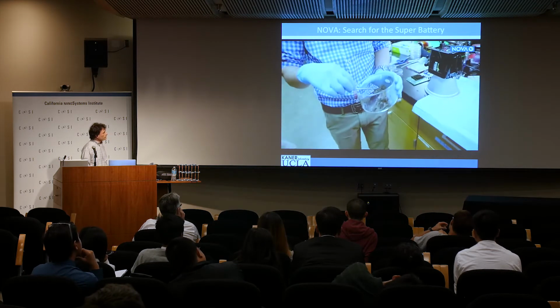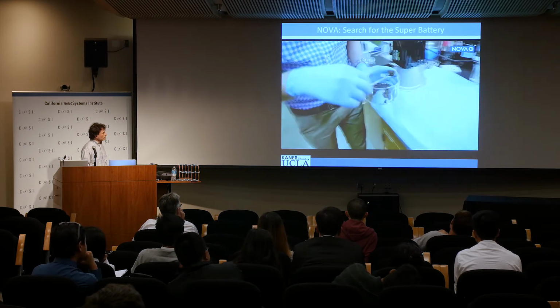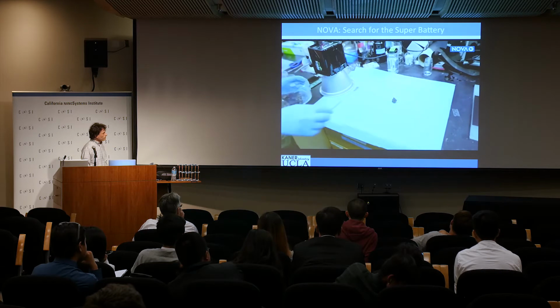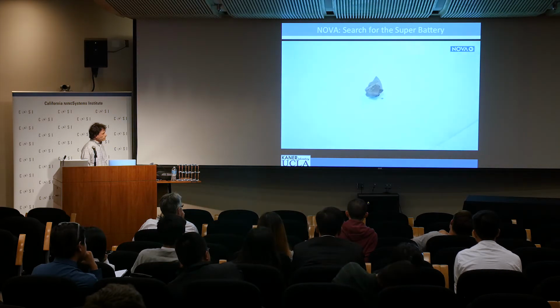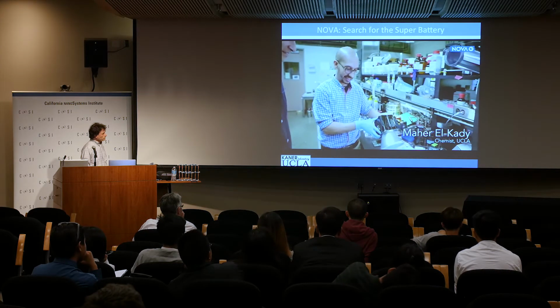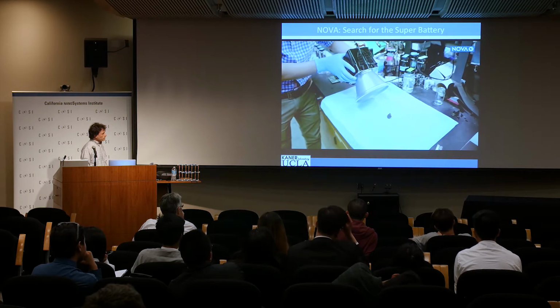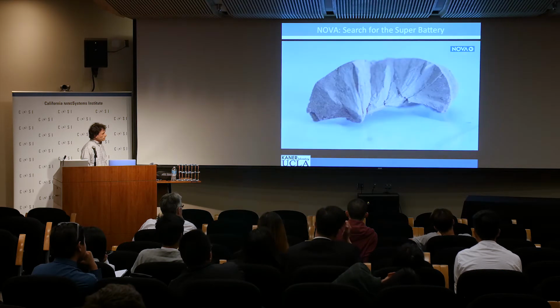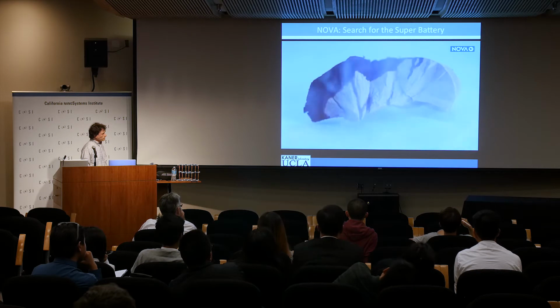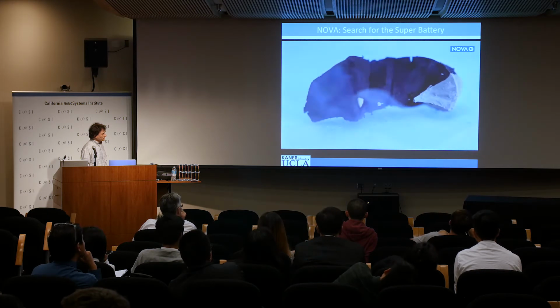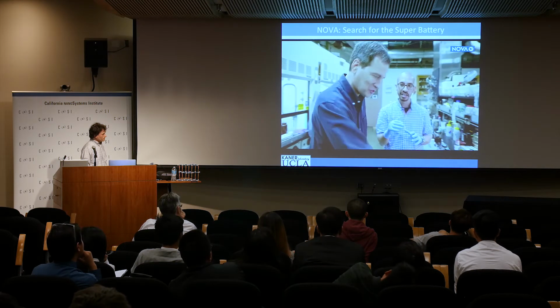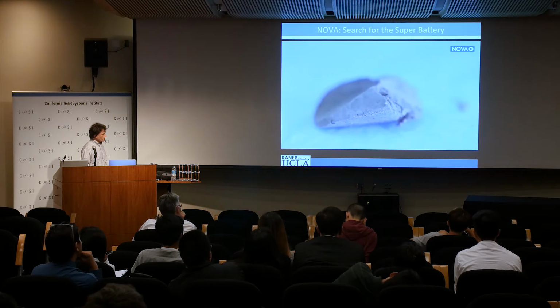This is a chunk of graphite oxide that was mixed with water and then freeze-dried. Maher El-Kady hits it with an ordinary camera flash. Big flash. So just watch what's going to happen. Okay. Oh! The pulse of light's converted to heat, burning away the oxygen and leaving behind graphene. That's graphene right there? So what's left over, we call it now graphene foam.